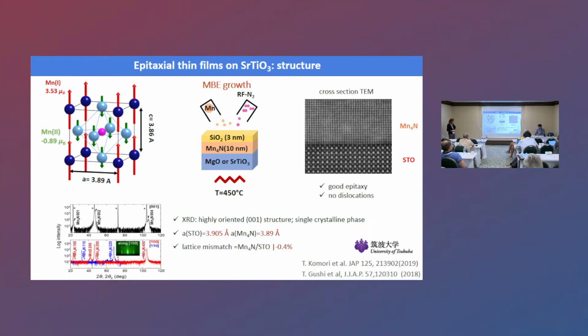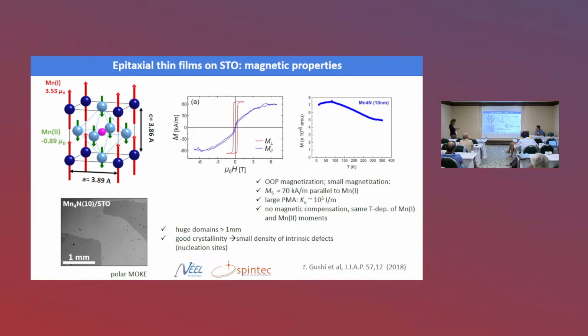Because of the very small mismatch between the two crystal lattices, they have a very nice crystallographic structure, as seen here by TEM measurements. So very good epitaxy with a very sharp interface and practically no dislocations. What about the magnetism? From the magnetic point of view, we find that the tensile stress gives rise to perpendicular anisotropy. So we have this 001 texture and also magnetic anisotropy.